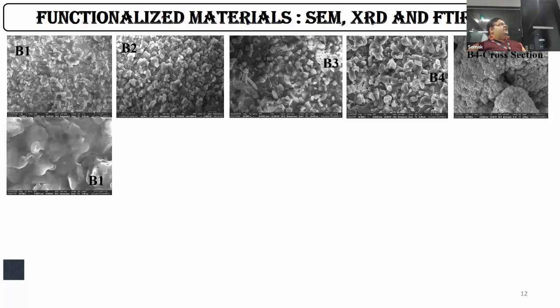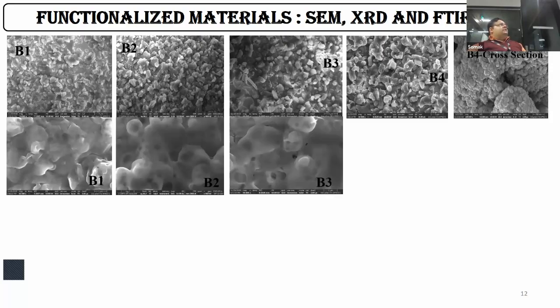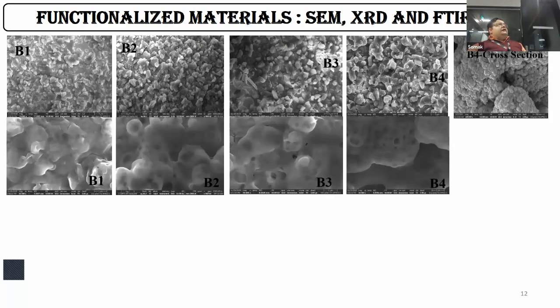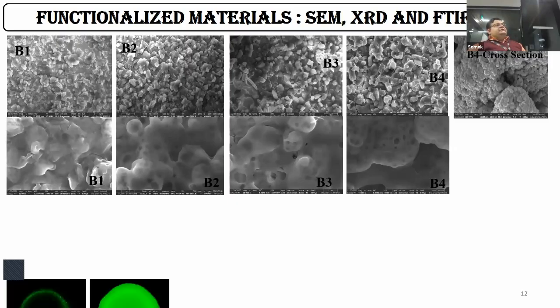Now we went into deeper correlation, and when we looked into the structures at a higher magnification, there are pores, strong larger pores, which actually can help imbibe the fluoride or water inside, and the material inside starts interacting with it.